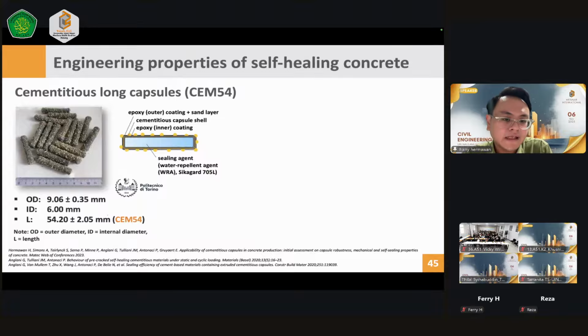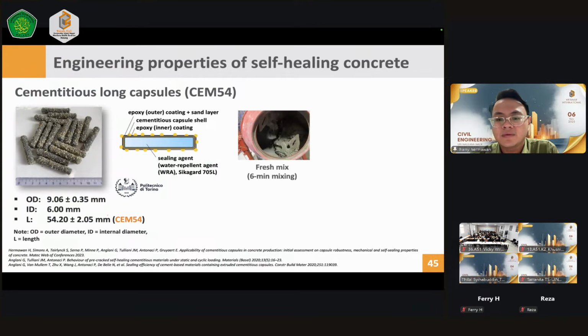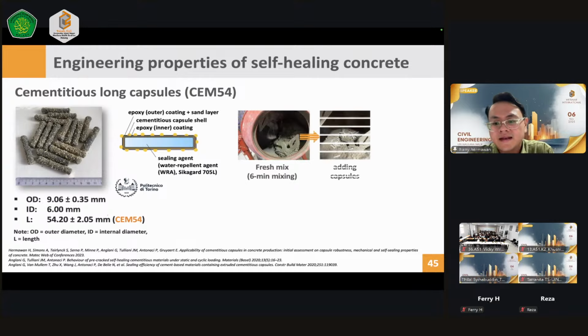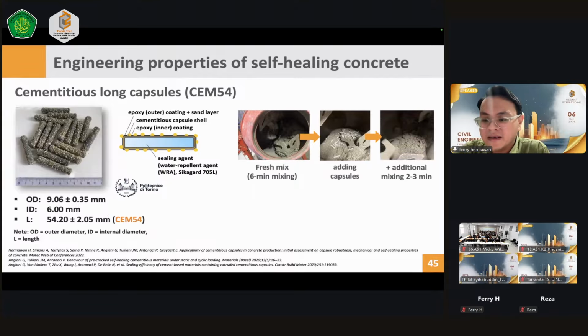Next, we also have another type of healing material, so-called macrocapsules. In this case, I'm using cementitious long capsules. This is a collaborative work with my colleagues from Politecnico di Torino in Italy. So how can we add these capsules into our concrete? Basically, let's first make our fresh mixture of the concrete. Then we add the capsules into this mixture, and we mix again for about 2 up to 3 minutes in order for the capsules to distribute homogeneously inside the mixer.